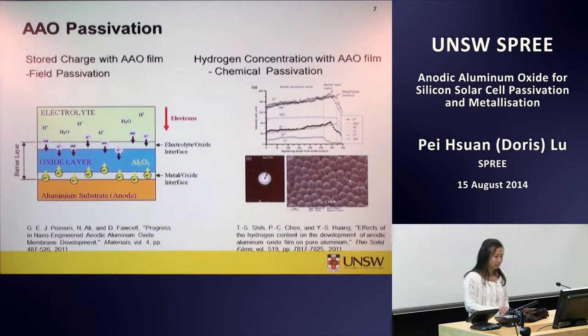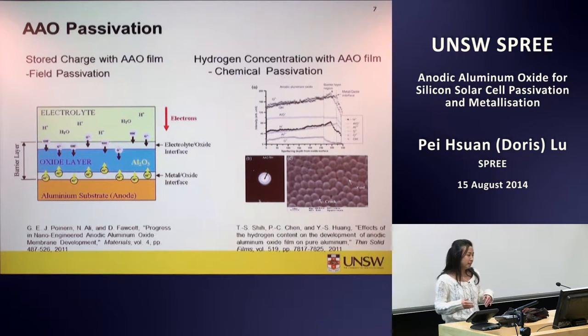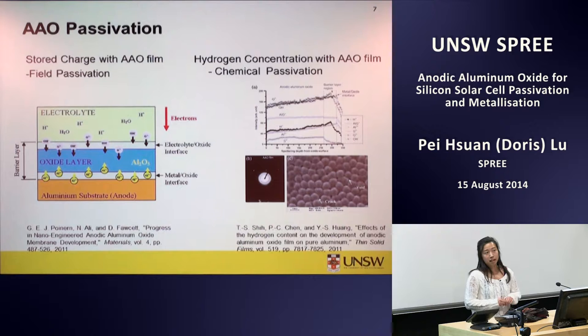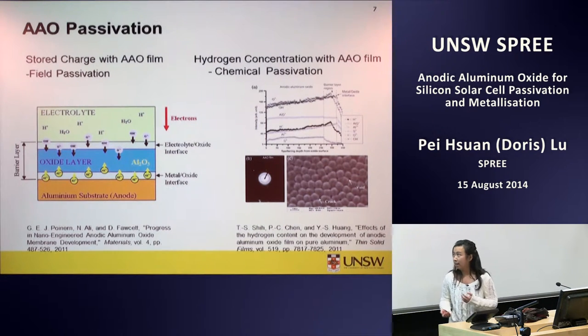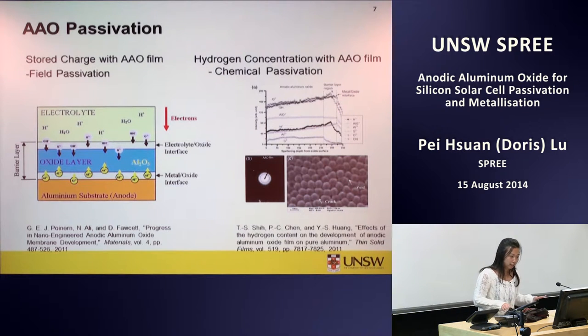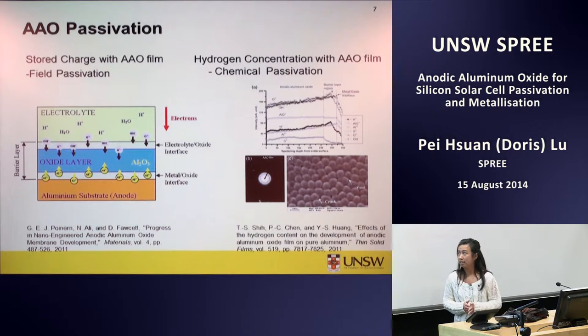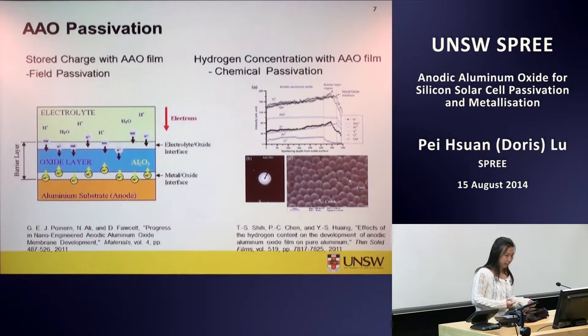I pretty much covered this slide. So basically, when the ions travel to the end of the aluminium and silicon wafer, there is a bit of an aluminium-rich layer, which has a lot of aluminium surplus, and this layer, the barrier layer, contributes the stored charge. The porous layer, people might call it the hydrated porous layer, because it usually contains a high amount of hydroxyl ions, which is a high hydrogen concentration.